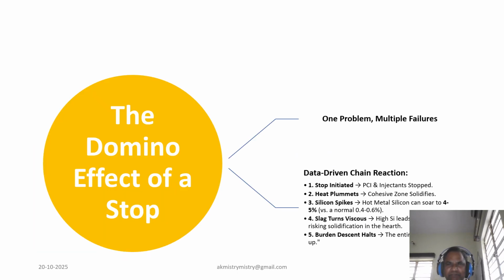So the initial freeze triggers a catastrophic chain reaction, a domino effect of failures. It starts simply: the stop is initiated, and pulverized coal injection and other injectants are switched off. Domino 1, heat plummets. The cohesive zone solidifies, just as we saw. Domino 2, the chemistry goes haywire. The silicon contained in the hot metal can spike from a normal 0.5% to an extreme 4% or even higher. Domino 3, this high silicon makes the slag, the waste product, incredibly viscous and sticky. Domino 4, that viscous slag risks solidifying right in the bottom of the furnace, in the hearth.